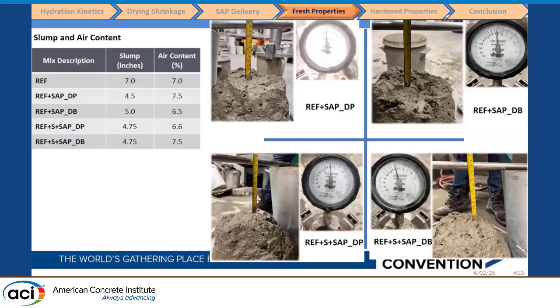We tested for fresh properties, the air content, which is very important for us, and then the slump. We found that for the reference mix, the slump was 7 inches, but with the addition of SAP, we found comparable results from both SAP delivery methods, the dissolvable bag and directly pouring the SAP. The slump for direct pouring of SAP was 4.5 inches, whereas using the dissolvable bag was 5 inches, which is close. And for the 30% slag replacement, we had the same slump value and slightly varying air content values.